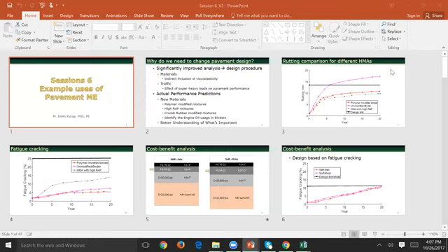So it's a 4E3 mix. The E3, meaning 3 million, is one of the inputs. PG is one of the inputs. And there are a couple more things that are inputs. Gradation, what's that? Gradation kind of thing, yes. And binder content and all that. So those are inputs, and it will give you a K value that you should be using. That's what we mean when we say project-specific. It's kind of an equation.